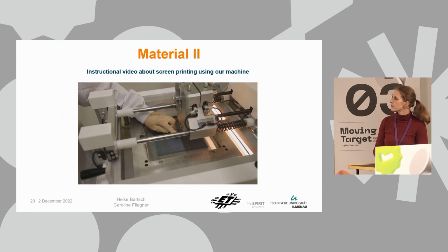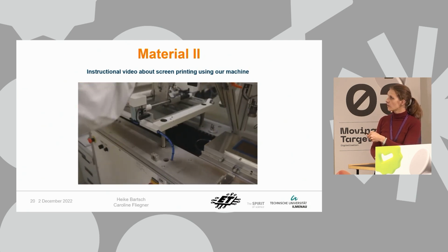At the same time, the goal is to bring the snap-off distance on the tape to 0. Here in the picture, you can see that there is still space between the screen and tape. Now the screen slowly descends to a snap-off distance of 0. As soon as the screen is on the tape, the snap-off distance required for printing is set and saved. Okay.